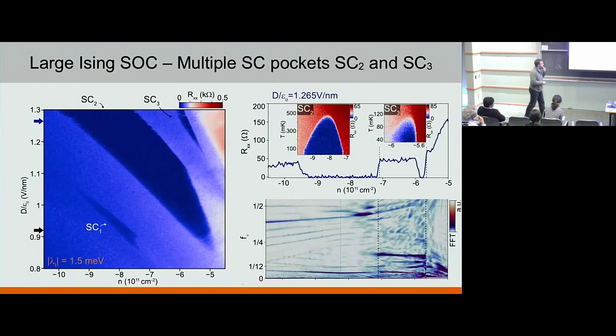So now, let's see what's happening in these two other pockets. We are essentially at a displacement field which is here, and we have two superconducting pockets, the big one which I showed you, and then this small one here. If you look at the evolution of the frequencies, you can clearly identify that there is some transition happening here because this line disappears. That's the end of this. The other end is here, where you lose the superconducting pocket. Similarly to SC1, this SC3 lives in this region here, but very close to the boundary where you have this rearrangement of the pocket.